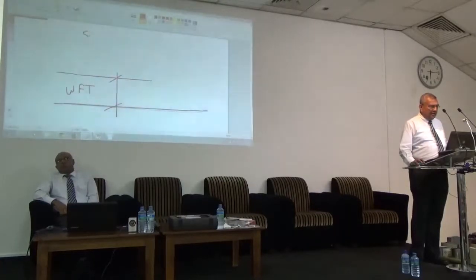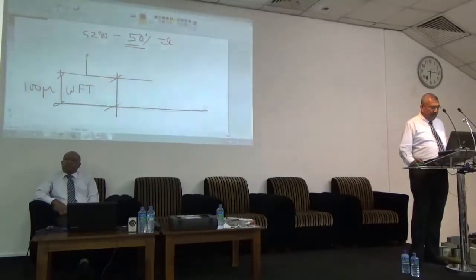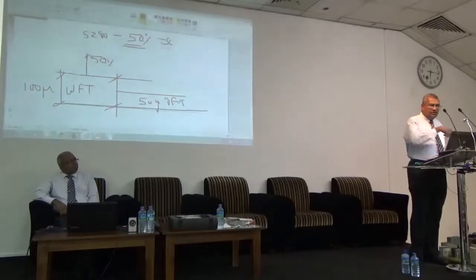Now if I put Sigma Cover 280 as a primer coat, I know the solid content is 57%. But I put 50% just for the example. The solid content is 50%. Now this is 100 microns. It will evaporate 50%. And this becomes 50 microns DFT. So whatever it has, it goes down according to the solids.